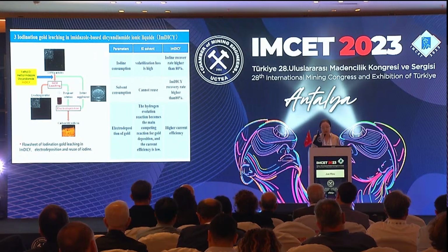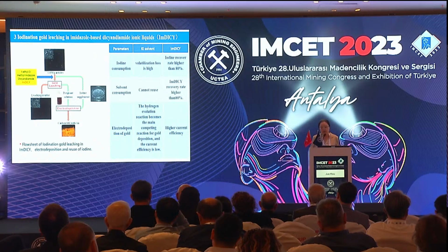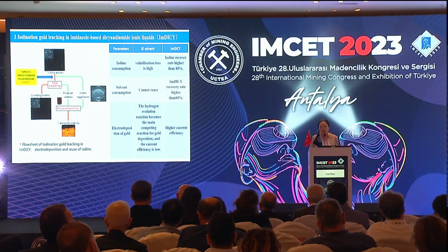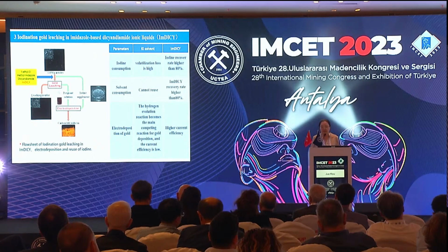And for electrodeposition of gold, in water, since it has a large amount of hydrogen, the hydrogen evolution reaction becomes the main competing reaction for gold deposition, and the current efficiency is quite low. If we use ionic liquid, since there's no hydrogen in it, or less hydrogen, it has higher current efficiency. Therefore, we can use electrodeposition to recover gold from the pregnant solution.